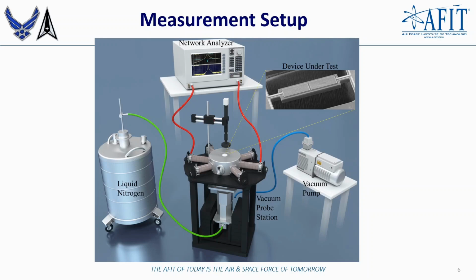So the vacuum pump here is used to maintain a low pressure environment at around 1 microtorr, effectively minimizing the air damping. A standard RF short, open, load, through calibration was performed to remove any errors from the cables and probes, ensuring precise data acquisition. And the network analyzer was used to capture the resonator's response across this temperature range, allowing us to assess the quality factor, resonant frequency, and overall performance in this extreme condition.